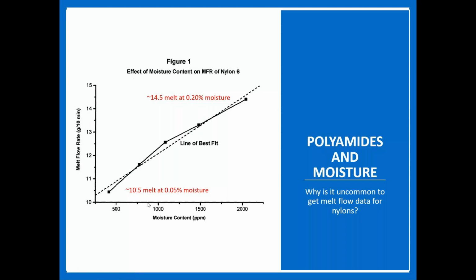If it gets all the way up to 0.2, still within the range we'd like to see you in for processing, and generally a max for what our suppliers will provide us, it jumps all the way to 14.5. So as you can imagine, it's all within the realm of acceptable moisture content, but I've jumped over 4 on my melt flow just because of that change in moisture. Now imagine it's been sitting for a little bit and maybe it's at 0.3 or 0.4% moisture. Or maybe we've dried it even further past 0.05 and maybe it's 0.01. The range of values you would get for testing it are going to be all over the place. If we were to try to do melt flow data, we would want the drying or the moisture content to always be the exact same, so that's not a variable within it. And that's hard to do. If you've looked at the testing you received for lots of nylon, it's going to come in that range. As long as it's under 0.2, which is generally the max that our suppliers will provide for us, they're okay.